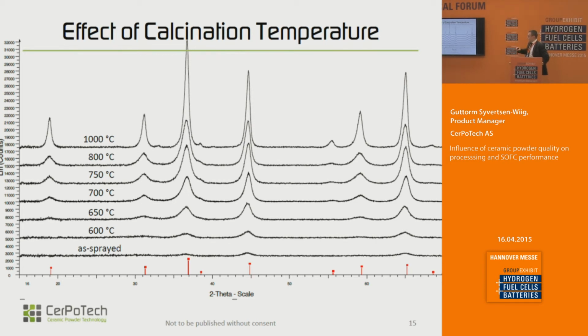One example on how the phase purity, or actually the crystallite size and phases, evolve with temperature. Down in the bottom here is an X-ray diffractogram showing the peaks of a quite well-known spinel material, magnesium aluminate, showing that you almost have amorphous powders when it's coming out of the furnace. And going up in temperature, you start to grow the crystallites, achieving larger particles. This is something we can tune, and when we are working with partners or customers and they desire a specific surface area or a particle size, we use these kinds of experiments to do this.